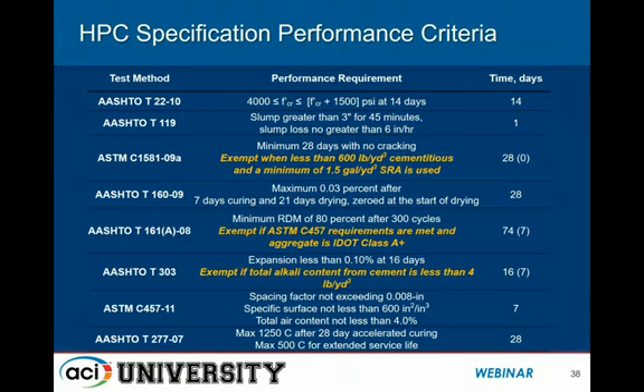The ring test, of course, as I mentioned, was employed with a 28-day minimum time to cracking. However, we also included an out. So if you have a mixture with less than 600 pounds of cementitious and a minimum dosage of SRA, you didn't have to run that test. We have had some success with that as well, because there are cases where either the time frame or the testing cost or something about running that test makes it more desirable to just use the mixture that we are confident in. And so it becomes somewhat prescriptive in that case.